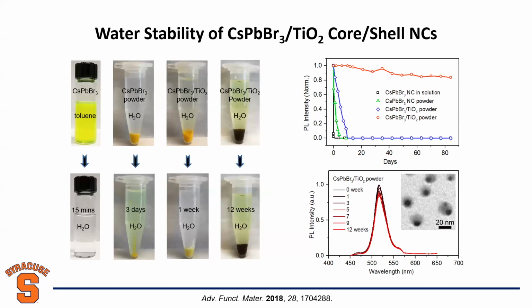If you shell it with titanium oxide in an amorphous phase, it can be stable for about a week. But after thermal calcination, we form crystalline phase TiO2. They can be stable for at least 3 months. You can go further than that, beyond 3 months. We saw in the paper at that time, this is the most water stable perovskite-based material reported to the community. But right now, probably there is a new record. So that's what we did. Okay, you can see this is a TEM image, which is great.